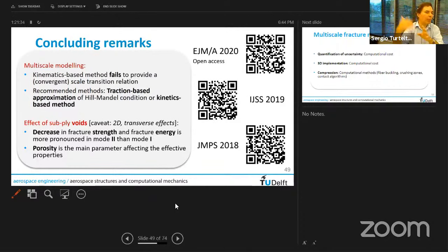You don't know a priori the properties of the RVE. In fact, you don't even know if your microscopic volume is an RVE to begin with. You need to establish that. So you need to take different volume elements of increasing size. And every time you take the average to find the effective properties, as post-processing of your microscale simulation. And once you notice that they don't change anymore, then those would be the effective properties. And then you would have established already the RVE.